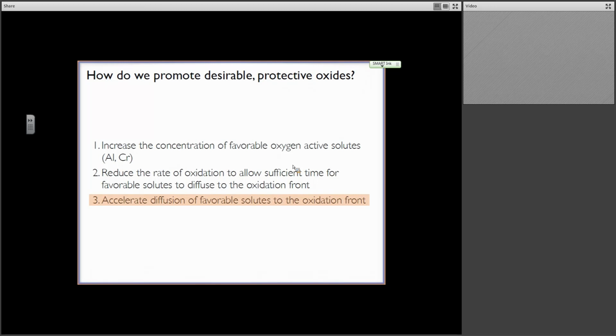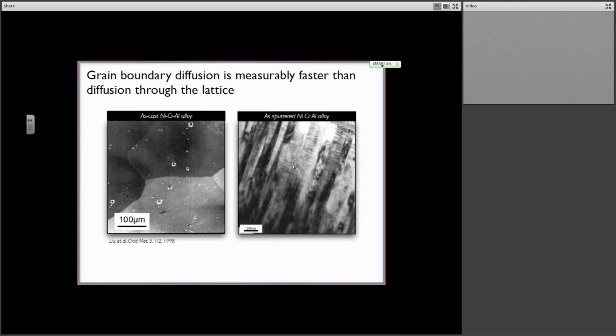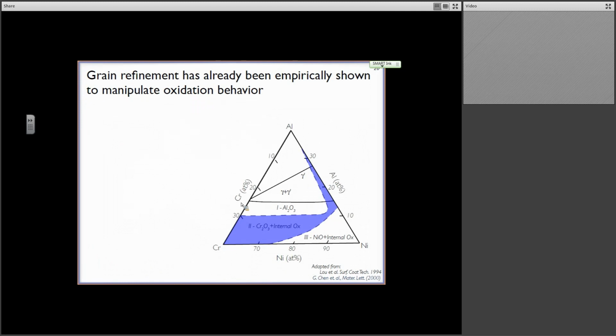And here we're working with the sputter-deposited thin films. It is actually quite interesting. So we know there's not a lot of ways that we can accelerate diffusion. Diffusion is a function of time and the chemistry and the lattice of the material itself. But there are things like grain boundaries that dramatically increase and accelerate the diffusion in a material. So the question is, if I take a coarse-grained nickel-chrome alloy like this, versus a sputter-deposited thin film with a nanocrystalline structure of the same chemistry, do these oxidize the same way at all? The answer is, no, they don't.